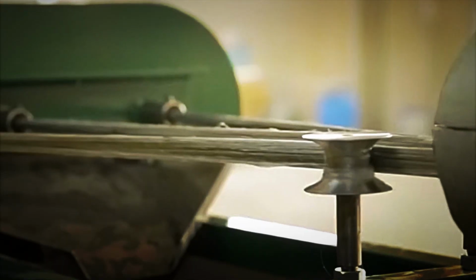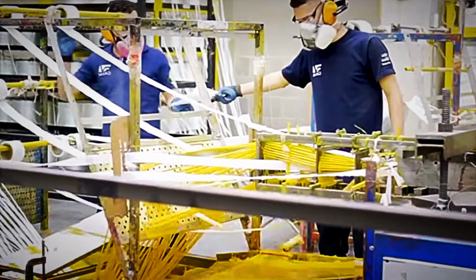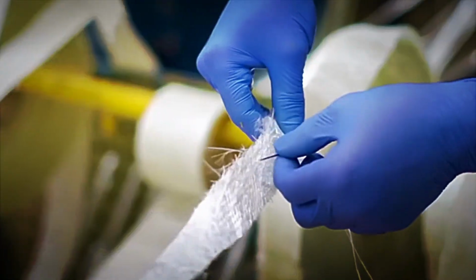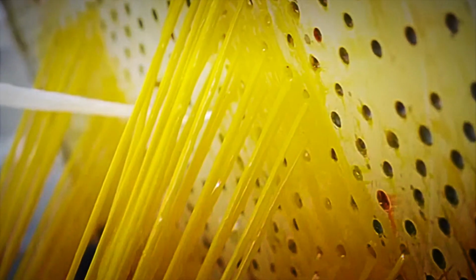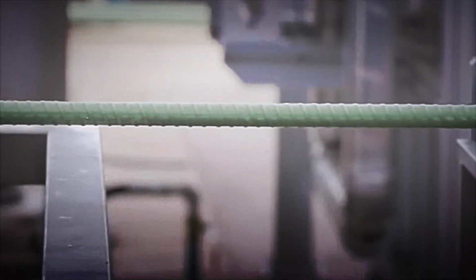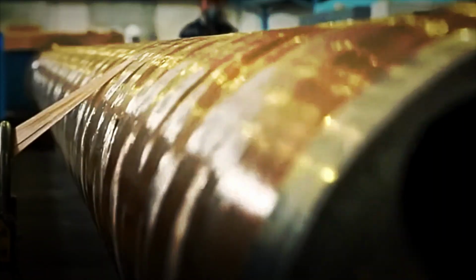A filament with insufficient tension tends to form waves or bend, creating areas with lower reinforcement density in the cross-section. On the other hand, a filament with excessive tension can stretch beyond its elastic limit or even break during the process. Both situations create heterogeneities in the reinforcement distribution, generating weak points or areas of stress concentration in the finished rod. To maintain precise control of this variable, modern lines incorporate tension sensors and load cells that continuously measure the force applied to specific filament groups.